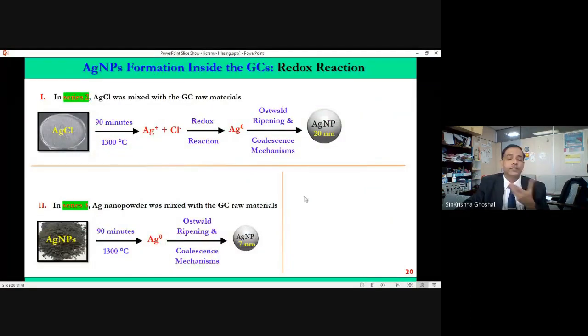So how does this happen? So there are mechanisms. The mechanism is called the redox reaction, reduction oxidation reactions in chemistry. Basically, chlorine has one electron, silver is positively charged. So this electron is captured by the silver. Silver forms the neutral atom. Many neutral atoms join together to form the silver cluster. And this silver cluster we call nanoparticle.